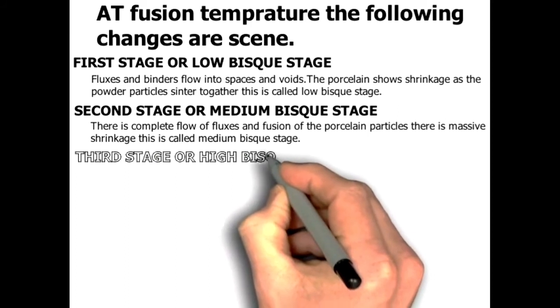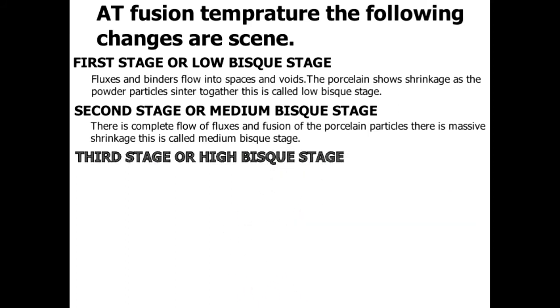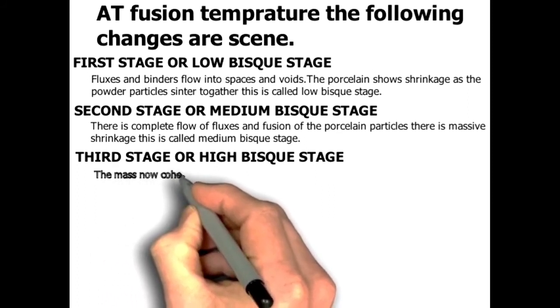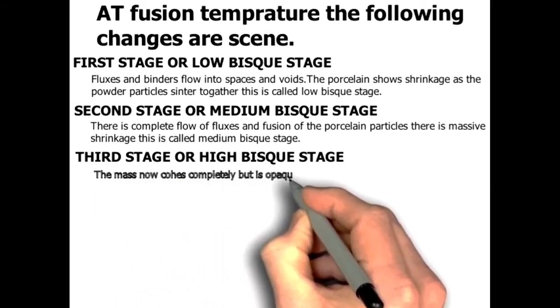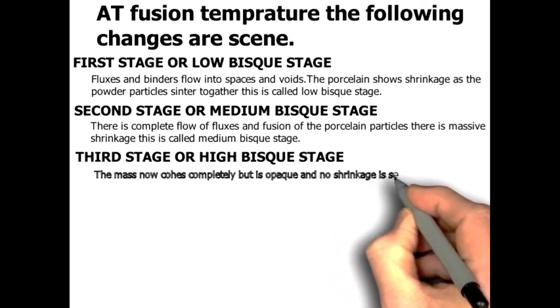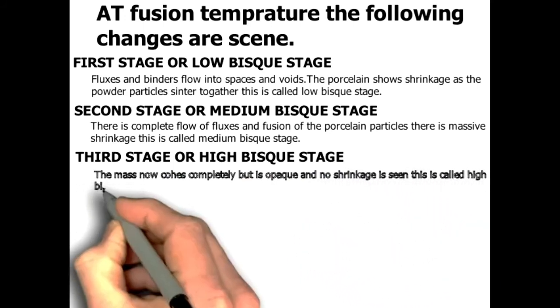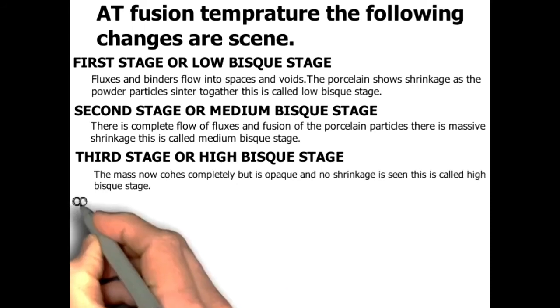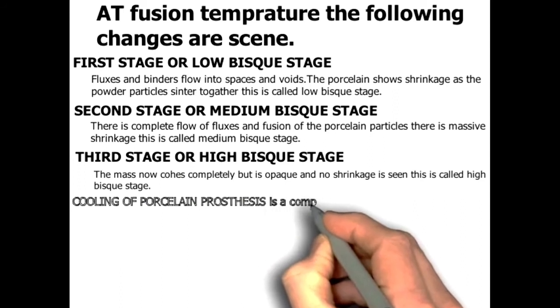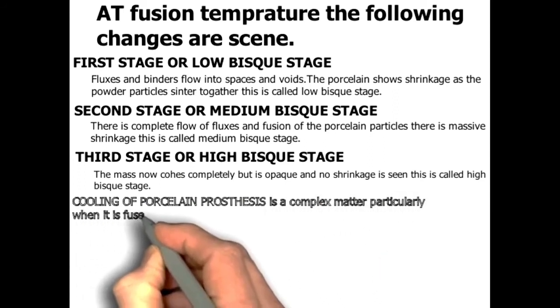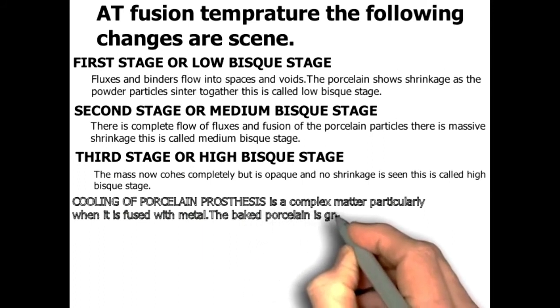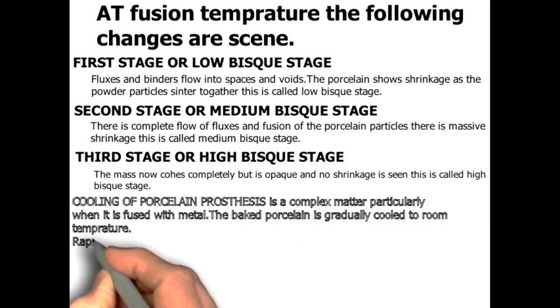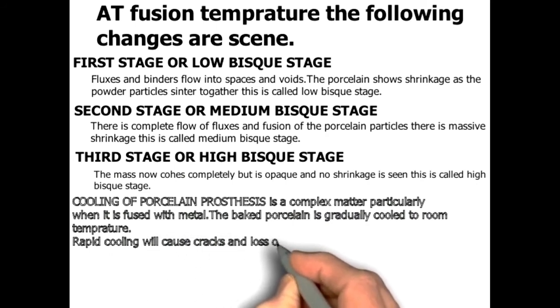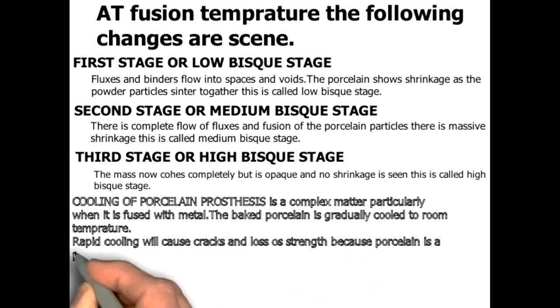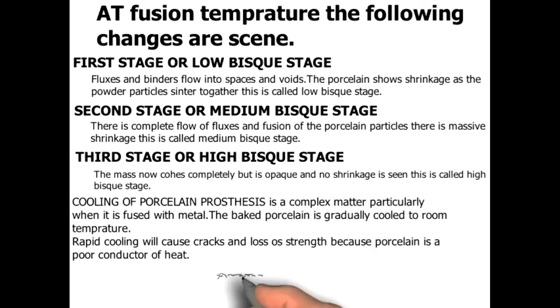Third stage or high biscuit stage. The mass now coheres completely but is opaque and no shrinkage is seen. This is called high biscuit stage. Cooling of porcelain prosthesis is a complex matter, particularly when it is fused with metal. The baked porcelain is gradually cooled to room temperature. Rapid cooling will cause cracks and loss of strength because porcelain is a poor conductor of heat.